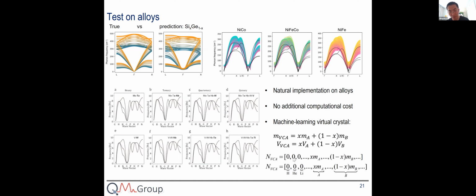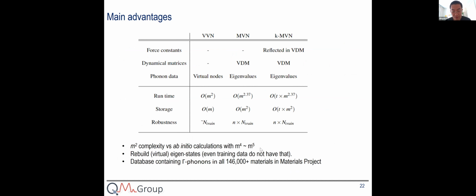If you change which components they are, you're changing different types of atoms, and then you can change the mass ratio by endowing the number there. By doing that, you can even calculate a phonon dispersion for a high entropy alloy with 5 different elements occupying the same site. You can just turn on 5 components simultaneously, and without a conventional ab initio method, where you need to do this Brillouin zone unfolding to get the final results, you can directly get the dispersions in 1 step.